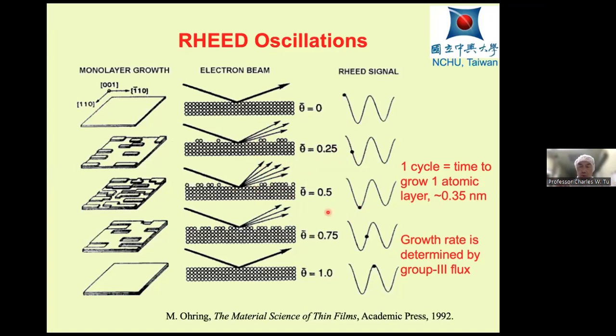And then as we deposit more material, these monolayer high islands coalesce, and so the surface becomes smoother again and the intensity increases. When we reach 1 monolayer, the surface is smooth again and the intensity is the highest. So 1 cycle corresponds to the time to grow 1 monolayer of material, 1 atomic layer, which is 3.5 angstroms. Of course, after 1 monolayer, some regions will be 2 monolayers and some regions 0, so statistically there is some roughening of the surface, and the intensity actually decreases somewhat.